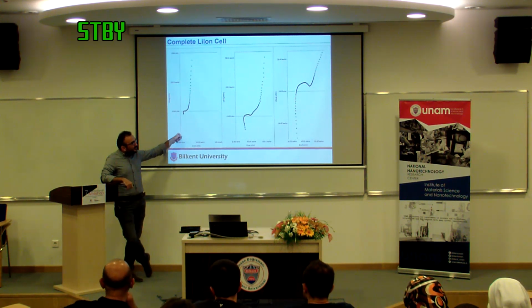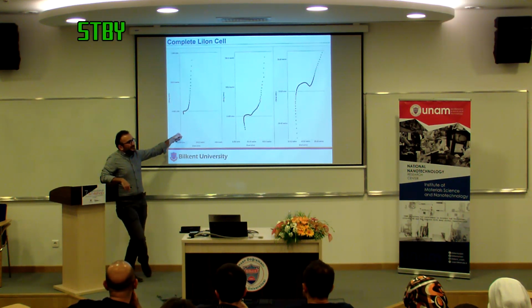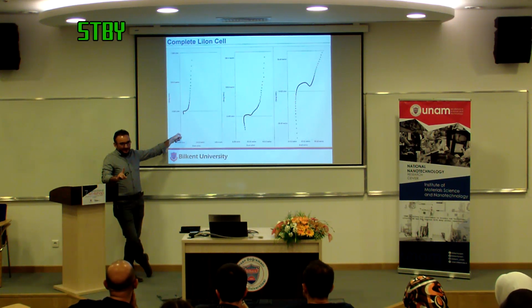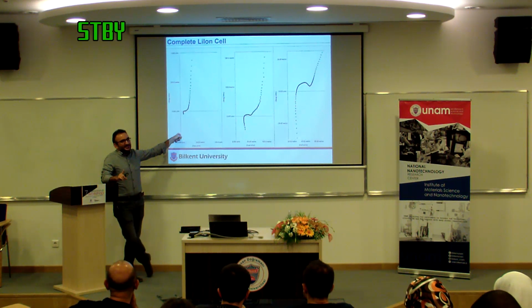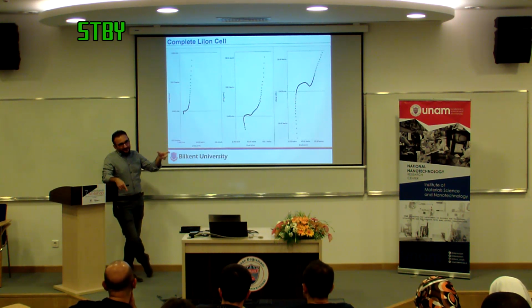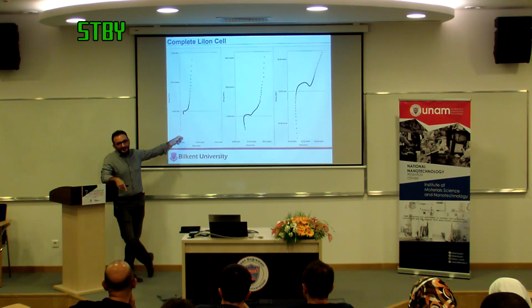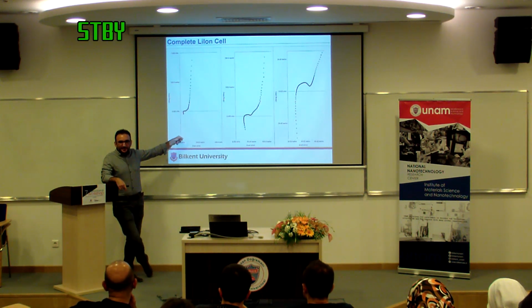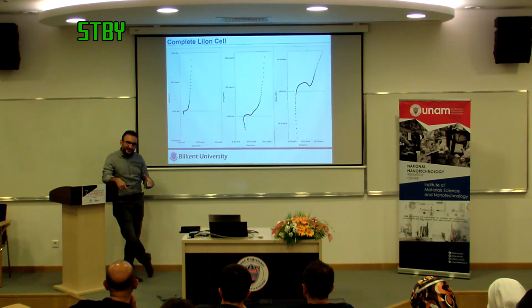Right, so this measurement is done all the way down to 1 microhertz. And 1 microhertz is 1 million seconds, which is close to 12 days or so. And I have to do that for 3 cycles. So this measurement was about a couple of months. And I had to keep my battery stable for a couple of months. So I did it at constant potential in a thermostatic environment.